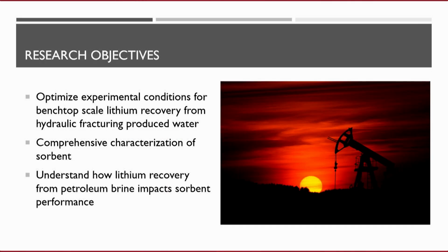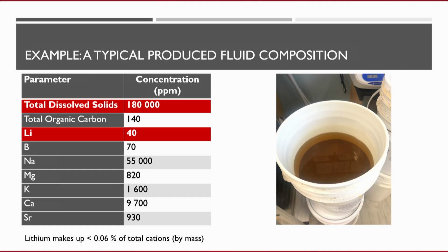So we are optimizing synthetic minerals to try to recover lithium from these brines, and that's what I'm going to talk about today. And trying to understand and optimize the chemistry of these materials is really the goal of this line of research in my research group. So again, here's a typical brine that I'm going to talk about here. You can see the salinity is 180,000 parts per million. Keep in mind the ocean's 35,000 ppm or so. So again, this is 5-fold, 6-fold the salinity of oceans. And in this particular case we have just a dusting of lithium, about 40 parts per million. Not a great resource on face, but again, if we can develop a material, maybe this can become an economic resource in Western Canada.